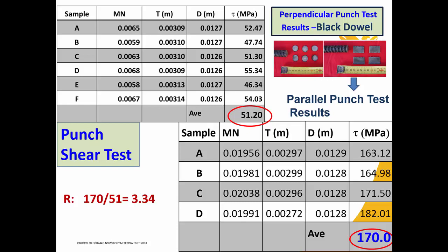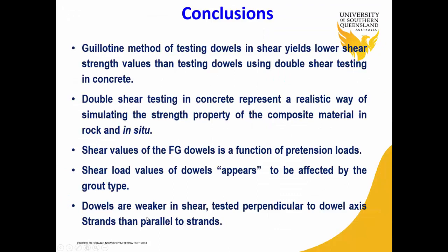Tests were repeated for black fiberglass dowel, and the ratio of 3.34 was achieved. So as a conclusion, the guillotine method of testing dowels in shear yields lower shear strength values than testing dowels using double shear testing in concrete. Double shear testing in concrete presents a realistic way of simulating the strength property of composite material in rock and in situ.